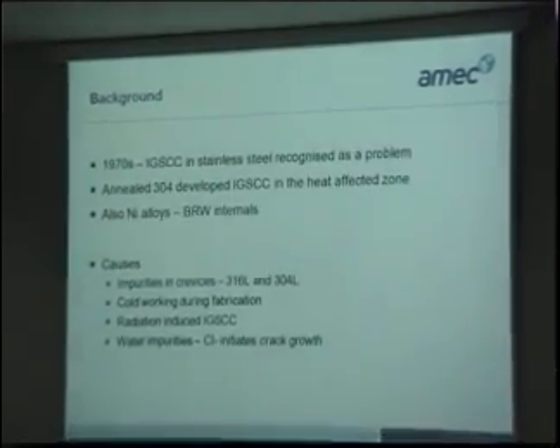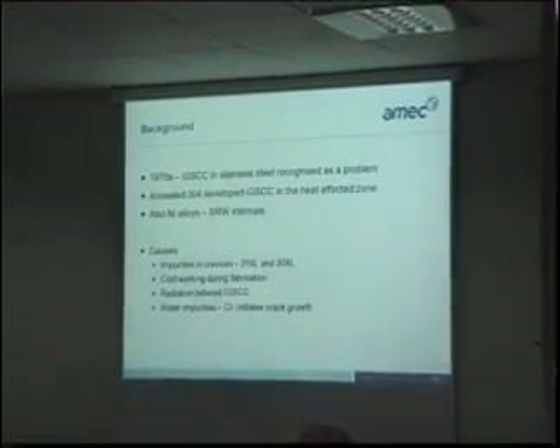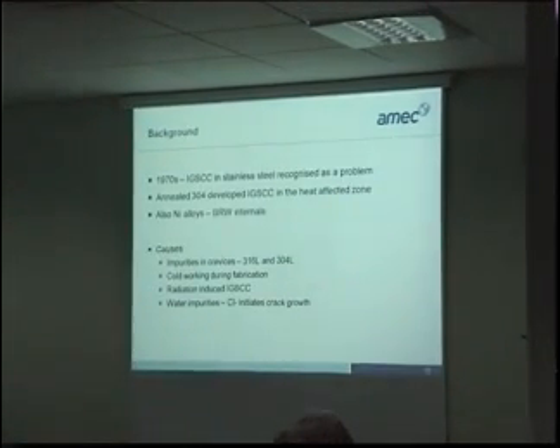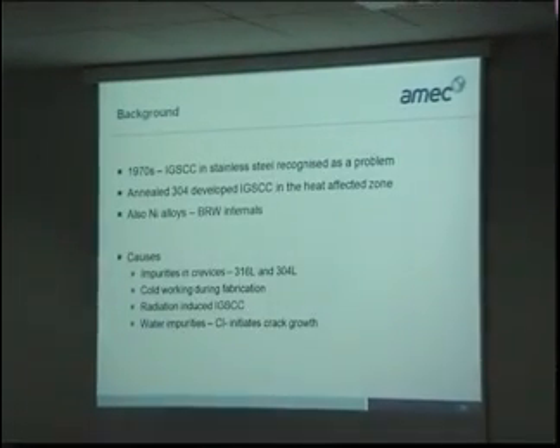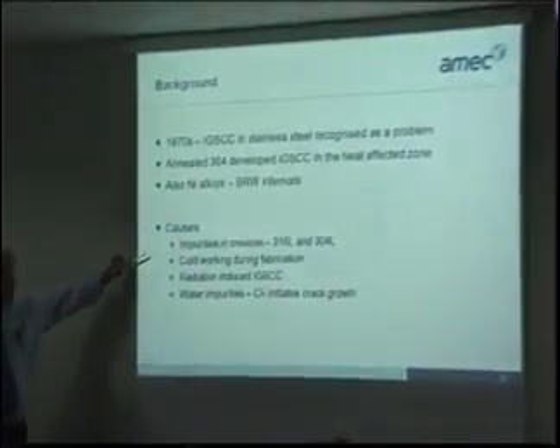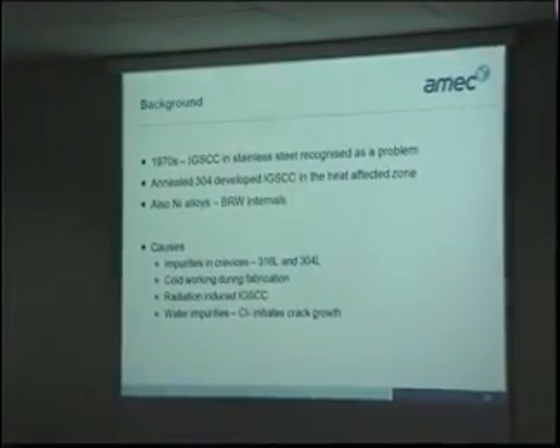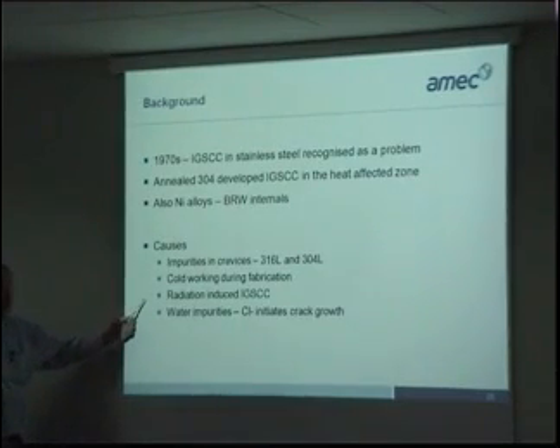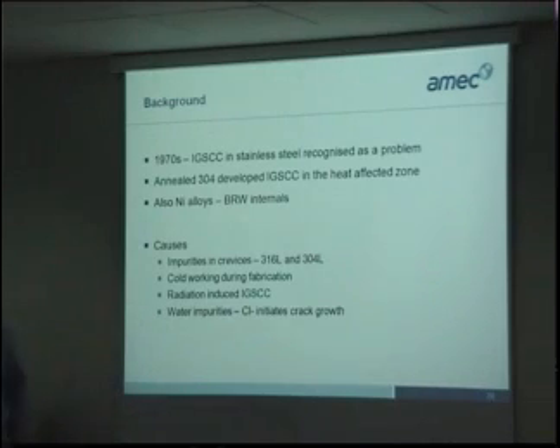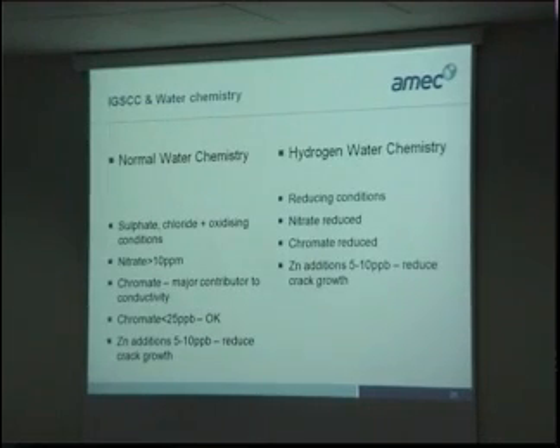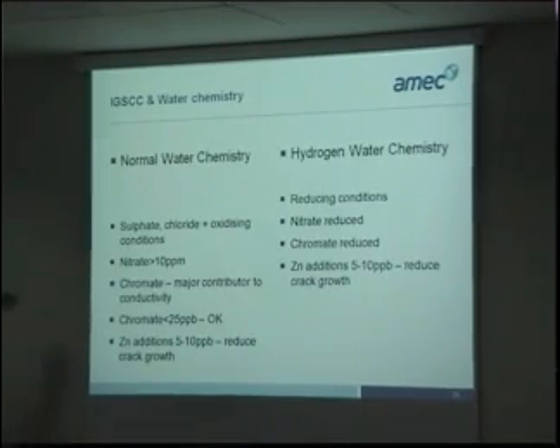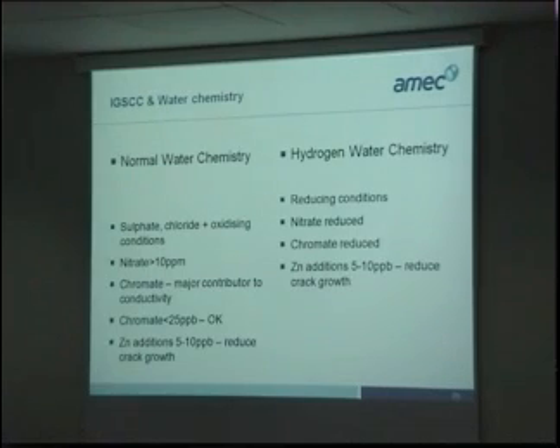But the background to this, back in the 1970s, stress corrosion cracking in stainless was always recognised as a problem. And annealed 304 developed stress corrosion cracking in heat affected zones, and also it was seen in nickel alloys, and it was due to either impurities in crevices or sometimes cold working during fabrication and the radiation induced cracking. And the water impurities, of course, chloride in particular, initiates crack growth. And so the two water chemistries were developed. But the early one was normal water chemistry, and basically this is just pure water with nothing added to it.